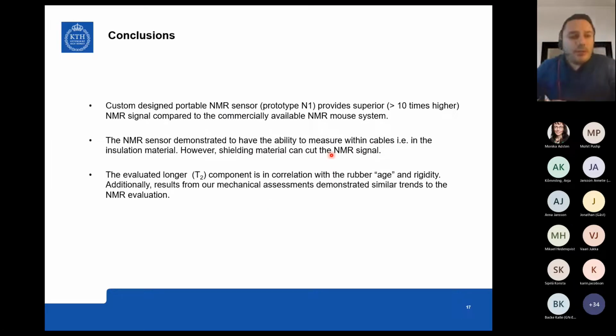Just to conclude about our findings, I think one thing which is quite unique with this study is that we've developed essentially a sensor which has a much higher magnetic field strength compared to the more commercial sensors which are available. And we can see that the sensor works on certain cable types. So the challenge here is mostly that when you have cables where you have a lot of steel shielding or mechanical shielding, which is giving the cable essentially mechanical integrity, and if it's ferromagnetic, it can actually alter the signals a lot. So those are the type of cables that we struggle with. But cable types which are, I would say, more polymeric and not so much steel involved in it, besides the conductor, those are more straightforward to analyze with the sensor that we have.